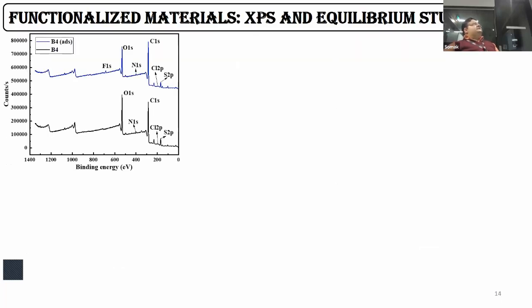We carried out an XPS analysis in order to ascertain whether the hybrid material is able to take the fluoride ions when we are actually putting it in a solution consisting of fluoride. We can see that F1s, which represents the orbital shells of fluoride, is getting adsorbed in the B4 beads.